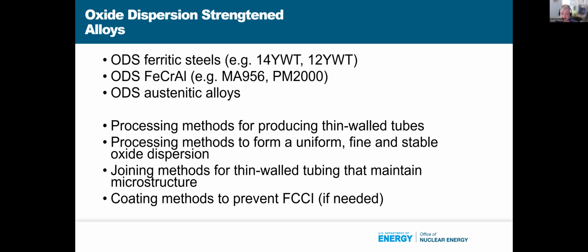There's a lot of nice data. If you can make a fine dispersion that's uniform in the material, there's a lot of nice data that shows that they have excellent and incredible radiation tolerance, but these need to be made into thin-walled tubes if it's a ferritic steel. And perhaps also there's the ODS FeCrAl. Maybe that could have a real application in lead reactors or lead fast reactors, but a lot of the initial materials like MA956 and PM2000 don't really have much of a fine oxide dispersion. So they don't have the 2 to 3 nanometer oxide size.